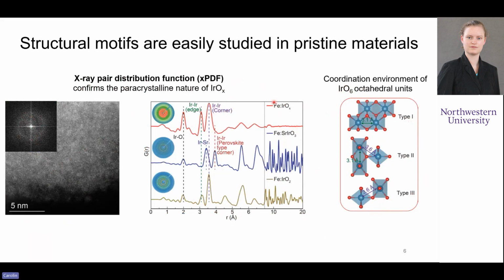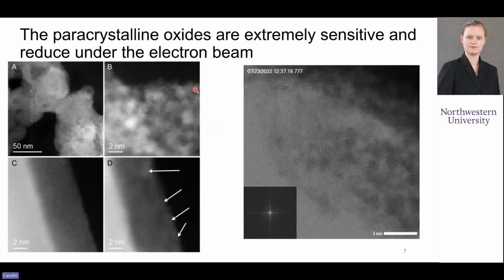And how does our iridium oxide match with that amorphous surface that forms on the strontium iridate? Before we get to do that, though, it turns out we run into an even bigger problem, which is that these paracrystalline oxides are exceedingly sensitive and reduce pretty much immediately under the electron beam, which is not entirely surprising. A noble metal oxide, when you shoot electrons at it, is going to reduce out, and that's exactly what happens here. So you can see over here, this square region, this is where an EDS map was collected, and you see the massive change in structure as you zoom out from there.